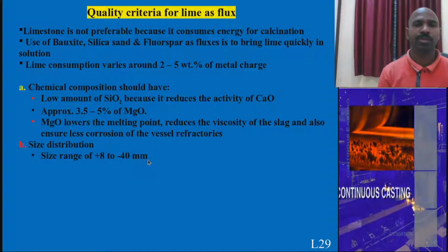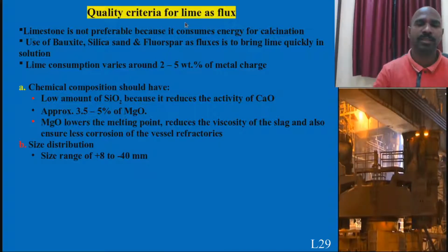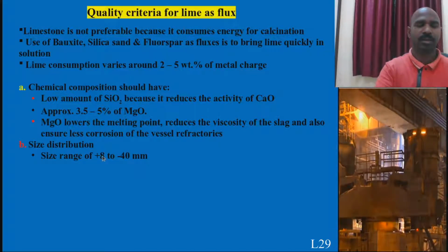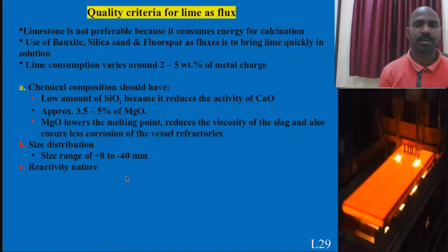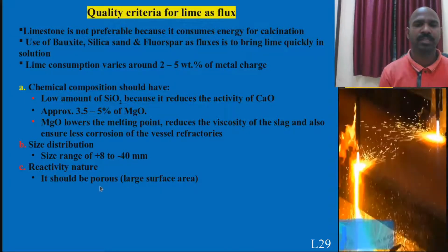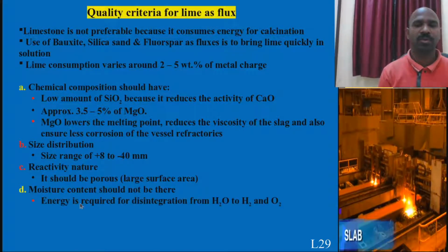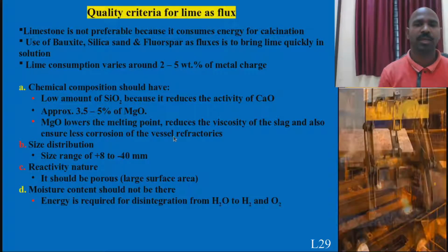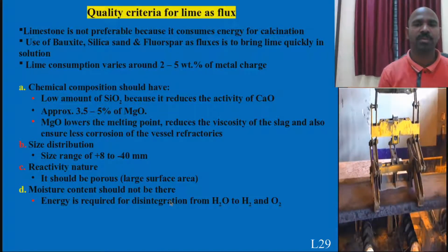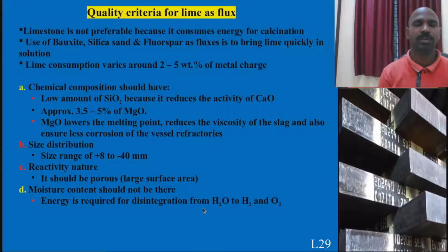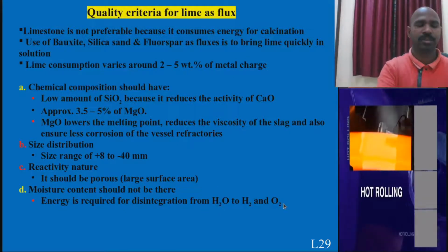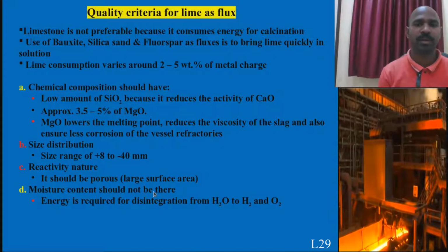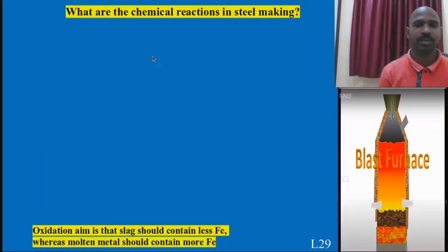For size distribution, the lime preferably used has a particle size of 8 mm to 40 mm. For reactivity, the lime should be porous in nature and free of moisture. It should have less moisture content, because if there is moisture, it needs to be dissociated into H2 and O2. That is why it should have less moisture content.